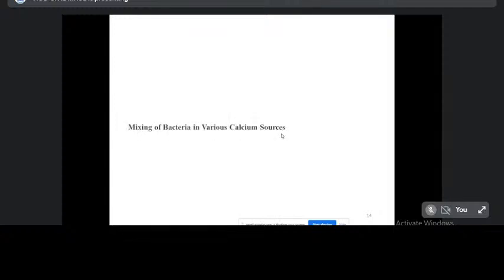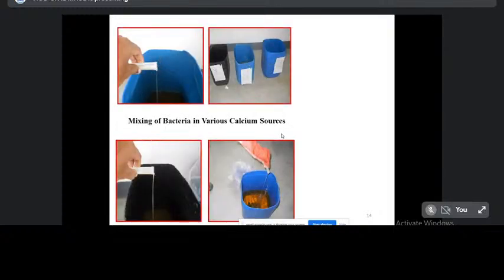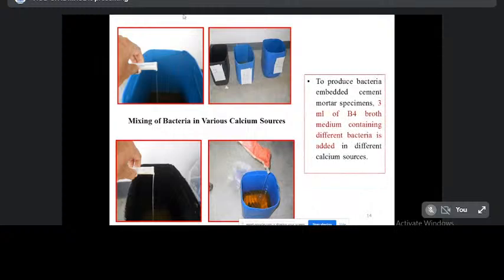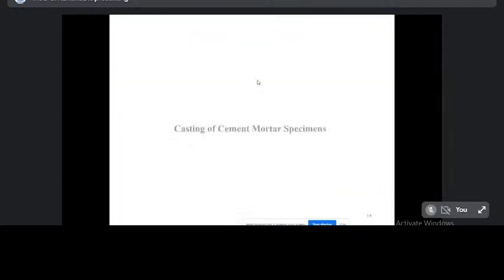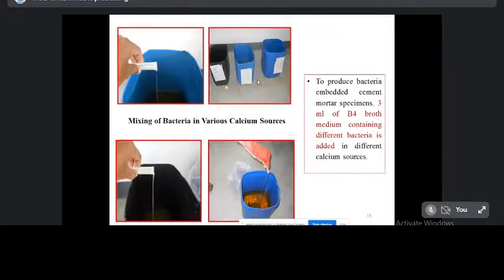Then the casting and preparation of cement mortar specimen. Actually, the B4 broth medium consists of grown bacteria. That grown bacteria contains 3 ml. 3 ml of B4 broth medium containing different bacteria is added to a different calcium source. I have prepared 4 calcium sources, and these 4 calcium sources are stored in separate containers. After that, these well-grown bacteria are mixed with these 4 types of different calcium sources. And this solution is used for mixing as well as the curing process of the cement mortar cube.